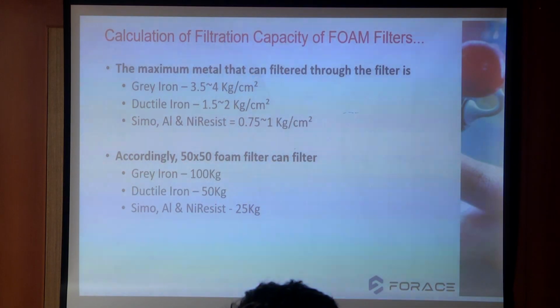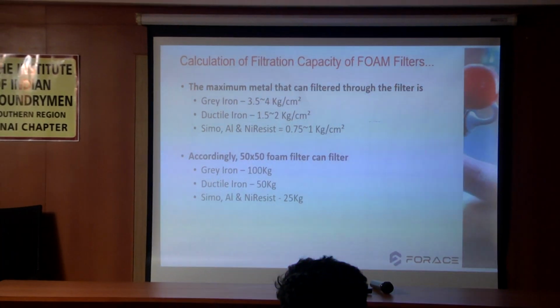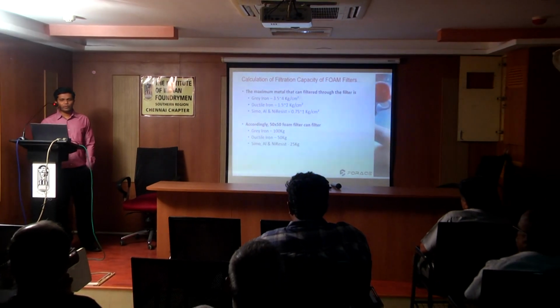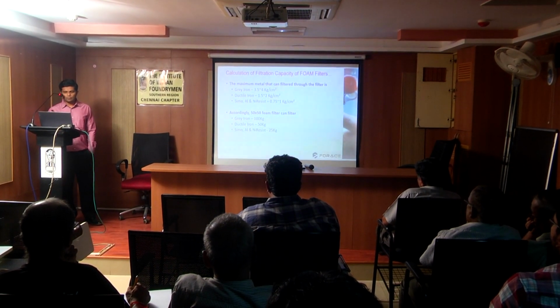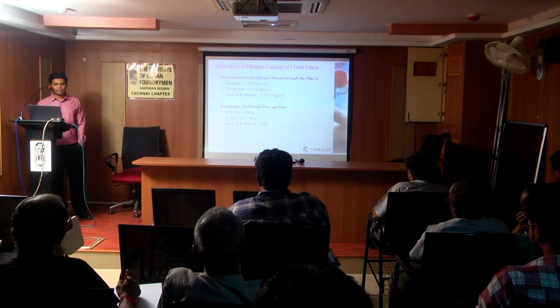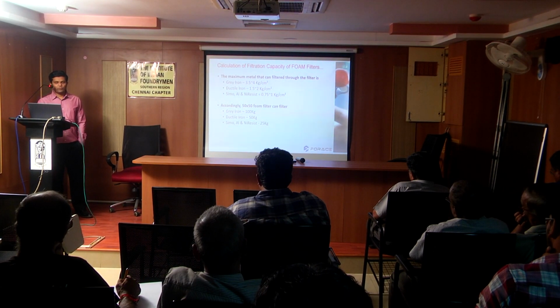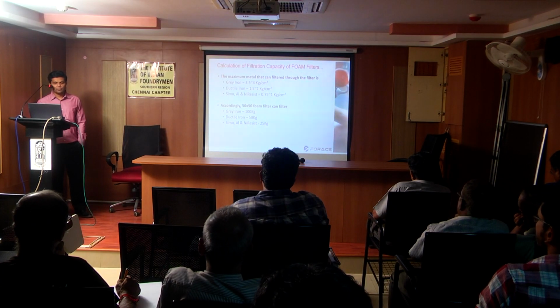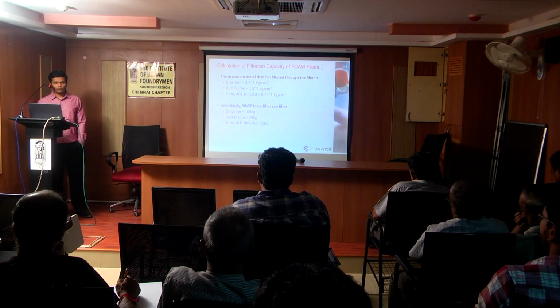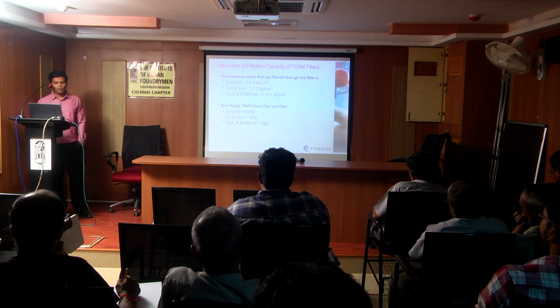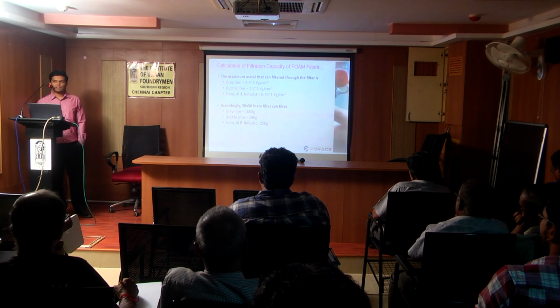So how to calculate the filtration capacity? If you consider a 50 by 50 filter and you are going to pour grey iron or CI metal through it, the filtration capacity will be around 100 kg, or the filtration rate will be around 3.5 to 4 kg per centimeter square. You just have to calculate the area, 50 into 50 into 3.5 or 4. That number will give you the maximum filtration capacity of the filter. Similarly, you can calculate it for the other metals. For ductile iron it will be half, around 50 kgs, and for Simo, Al & NiResist or aluminum castings, it will again be half, around 25 kgs.